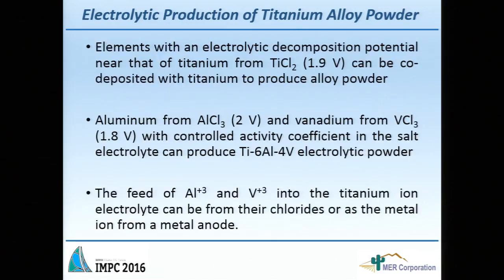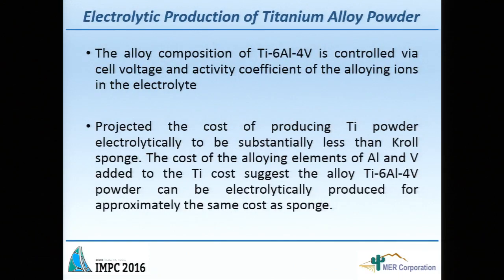Okay. The other thing we did is that we demonstrated that we can produce the alloy. The aluminum and vanadium potentials are very close to the titanium potential. So by controlling the activity coefficient of this element in the electrolyte, we can produce the alloy. And very important is that we projected the cost of producing titanium powder electrolytically. And actually, I was involved in that part of costing the process. And it came to be fairly similar, or actually less than the cost of the sponge.